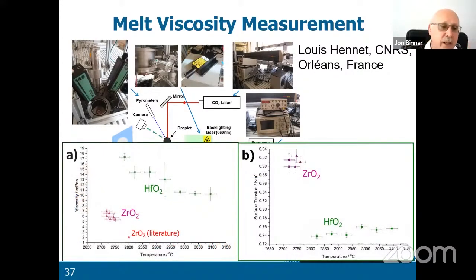So on the left-hand side, you have got viscosity versus temperature. And on the right-hand side, you've got surface tension versus temperature. And you can see hafnia is more viscous than zirconia, and zirconia has a higher surface tension than hafnia. And you can see also that the viscosity decreases with temperature, which is exactly what you would expect.